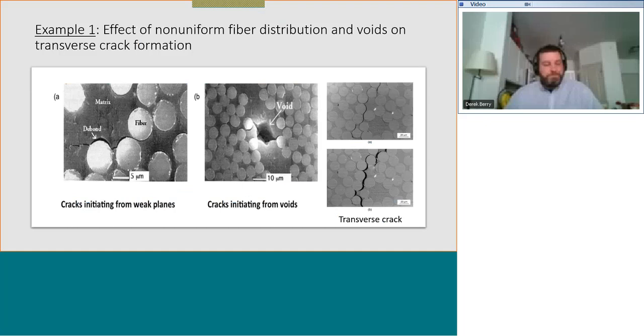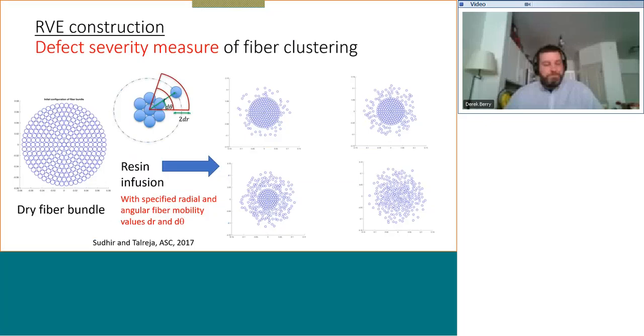Okay, I'll do 2 examples, and it's going to be too technical if I go into details, and I know that time is limited. So there are these populations of the microstructure that you see there that have defects such as fiber non-uniformity in distribution and voids. Next slide, please. Yeah. One of the important characteristics of the internal structure of the composite is how fibers are clustered together. If they are uniformly distributed, they usually provide good response. But if they are clustered, then they are initiators of the first failure, mostly cracks in the interface and in the matrix polymer between the fibers. Next slide, please.